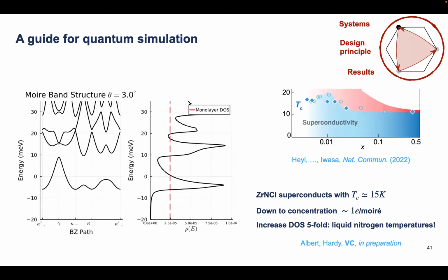What does it include? What do you consider? So monolayer form factors: whether there was some Berry curvature to begin with in the material, that we consider. And the second thing we consider is what is the shape of the superlattice potential. If it's honeycomb, then it's easier to create a topology. But it could also be that when you have more than just one degree of freedom and you have a spinor, then it's possible that just interlayer coupling by itself induces topology. So you don't need form factors in the material.